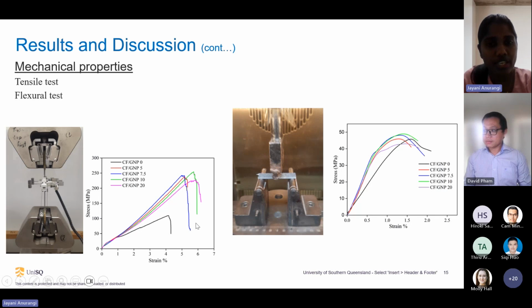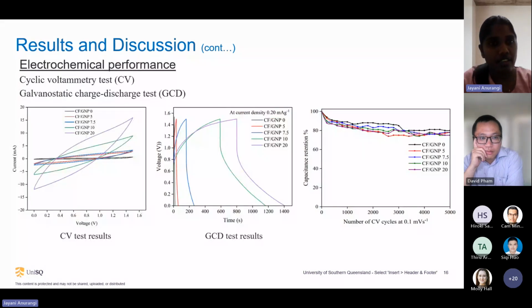According to these results, you can see after GNP coating, the ultimate tensile strength has significantly increased. However, in the flexural strength, I didn't notice that kind of significant improvement, but tensile strength was significantly improved after GNP coating. Here I have illustrated the results of the electrochemical properties. Here also you can see after GNP coating, the capacitance value has increased, and also specific energy and energy density have increased significantly after